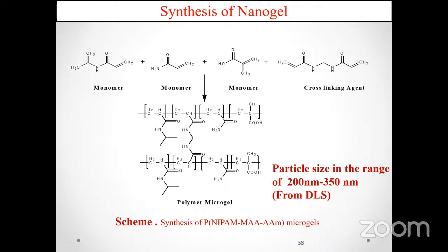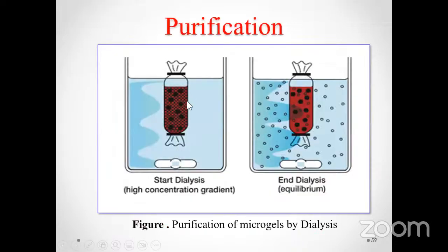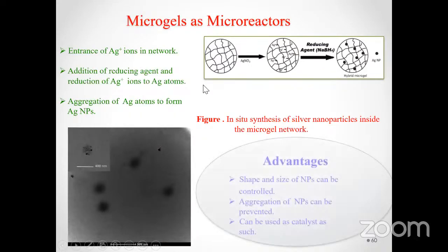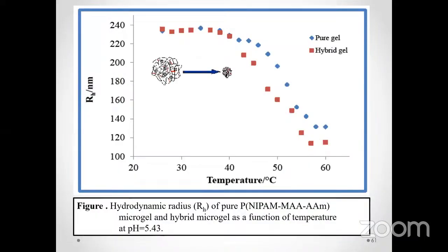Now, I will talk about the chemical sensing or the optical properties of the metal nanoparticles. We have prepared a nanogel system by suspension polymerization, and after suspension polymerization, this was used for the synthesis of silver nanoparticles. And the STEM image shows the formation of silver nanoparticles. Once the nanoparticles were formed in the hydrogel systems, these hydrogels were also found to be temperature sensitive, as shown in this figure, that as we increased the temperature, the size of the hydrogel particles decreased. The chemistry of this process I have discussed earlier.